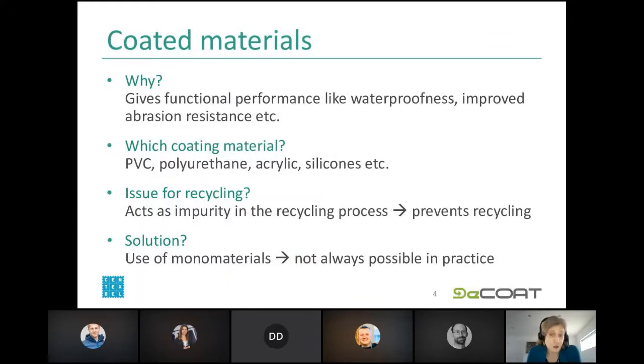So why do we use the coatings? It's actually to give a functional performance to the materials, like waterproofness or improved abrasion resistance. So it's really to meet the requirements during the use phase of the product. Which kind of materials are these? It was already mentioned, it can be PVC, polyurethane, acrylic ones, it can be silicones and so on. So why do these coated materials pose an issue for recycling? It's actually because this coating acts as an impurity in the recycling process and it really prevents recycling. So nowadays these objects end up in landfill or are incinerated.